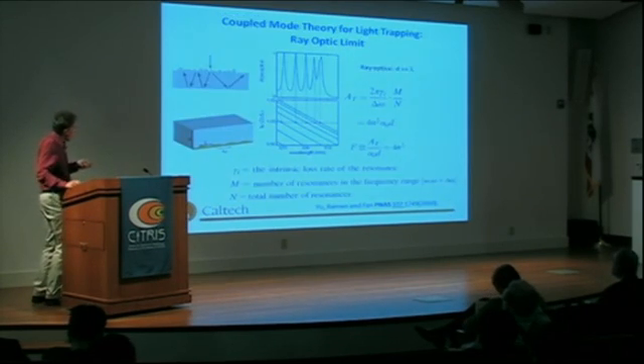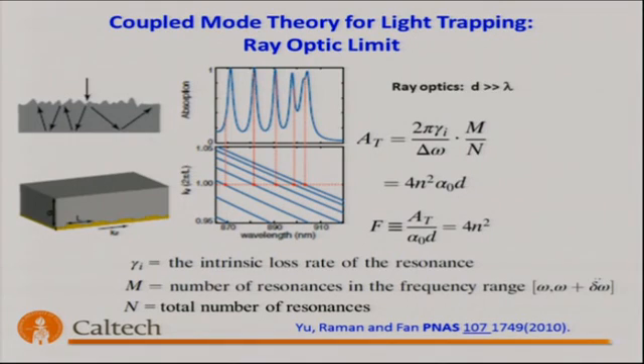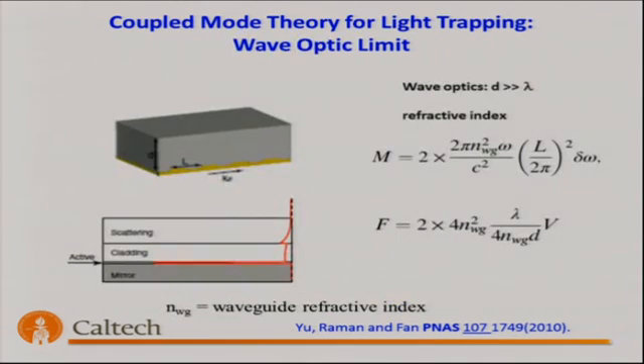And Shanhui also developed recently a model in terms of coupled mode theory, temporal coupled mode theory, that views an absorption limit in terms of the number of modes and the spectral bandwidth of modes. If you use Shanhui's model in terms of discrete modes from coupled mode theory, you can arrive, for a homogeneous dielectric medium with a refractive index n, at exactly the same result as the statistical ray optics picture that Eli developed in the early 80s. But what's interesting is what happens when you now go into the wave optic limit, where the waves that are propagating through the material are not all plane waves. And in some cases, these waves can be highly confined.